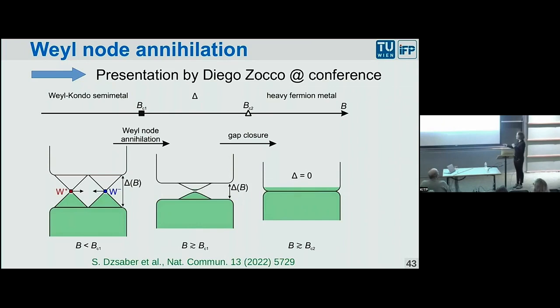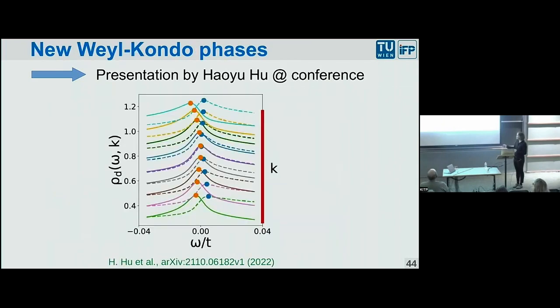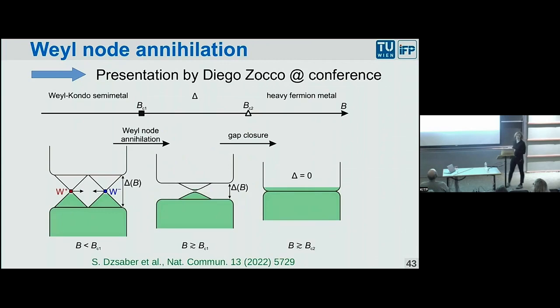So once you have reached a certain field, the effect is totally gone because the Weyl nodes are no longer there. And the second proof is that if we measure at high temperatures, where all this interaction physics isn't yet there, there's also nothing. So you need the low temperature, so the interaction physics builds up, and then you need zero field, so it's there. But if you kill the effect with field, it will be gone again. So it's really quite obvious this Berry curvature is there and is doing it.